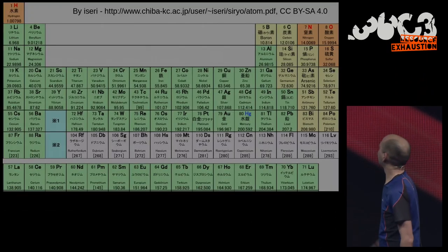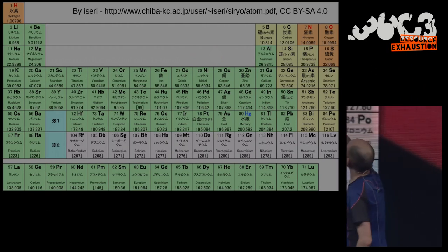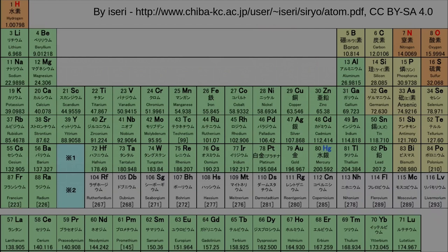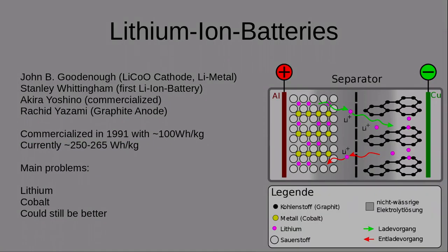If you remember this table, storing it in graphite has a problem. You see up there carbon. Carbon has a weight of 12. And when you store lithium in these layers, you need about 6 carbon atoms to store 1 lithium atom. And the carbon atoms together, six carbon atoms, have a weight of 72. The lithium atom has a weight of 7. So the carbon is about 10 times as heavy as the lithium. So obviously, this is not ideal. But it took a long time just to max this out. These days, I think they're at around 90% or so of the theoretical capacity. So if you want to do something with graphite, you cannot improve this much more.